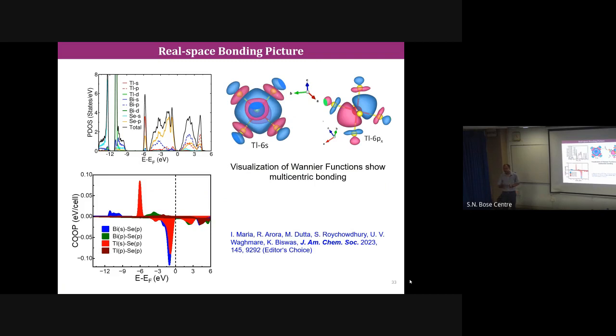For example, all of you know about the oxygen molecule. The bond order is 2, right? If I go to superoxide, O2 minus, it becomes 1.5. Peroxide, O2 2 minus, it becomes 1. So the electrons fill up the anti-bonding orbitals more and more. Here, electrons fill up this anti-bonding orbital, which is created by the expression of the lone pair, which creates this local distortion. So that anti-bonding filling gives you the extended structure electron deficient, making it metal. So this is the origin of metavalent bonding in this compound.